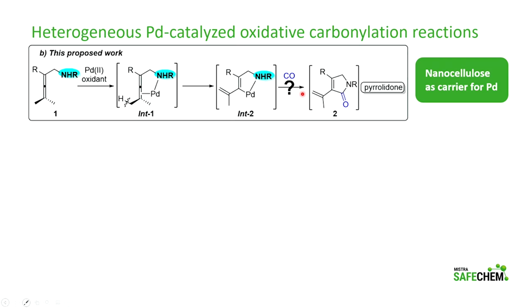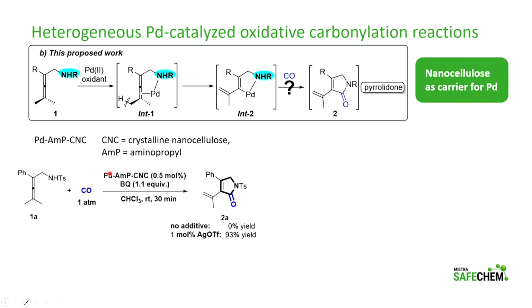And the question is, can we now react with carbon monoxide? Because carbon monoxide is a very useful reagent since it can be generated from carbon dioxide via reduction, as also discussed previously. And then we could get pyrrolidones. In the first attempt for this reaction, and I should mention that the linker AMP, aminopropyl, is used to tie palladium to the nanocrystalline cellulose, we got no yields. But look here what happened if we add just 1 mole% of silver triflate, that is twice the amount of the palladium catalyst, then we get a very high yield. So there's a dramatic effect of addition of silver in this reaction.